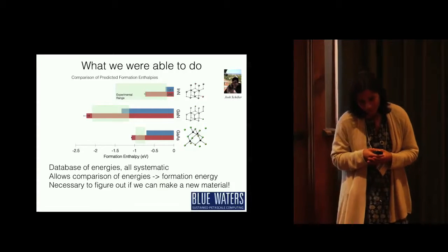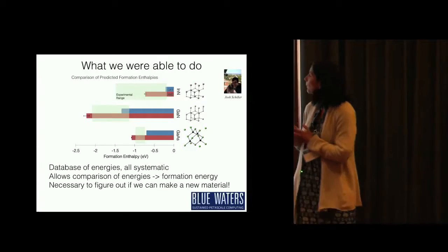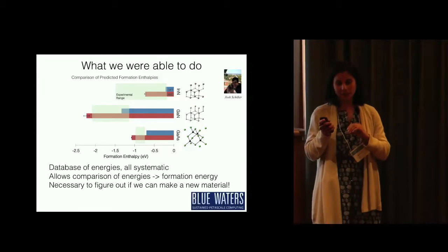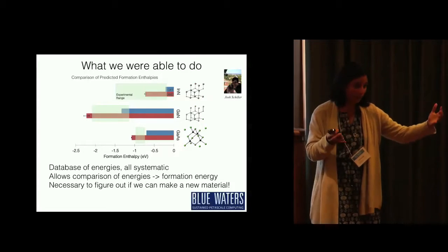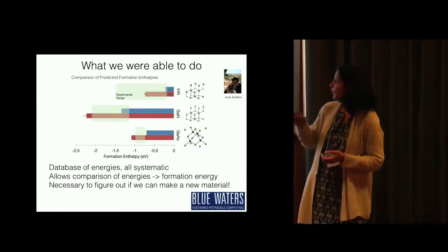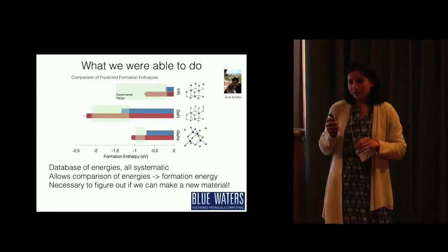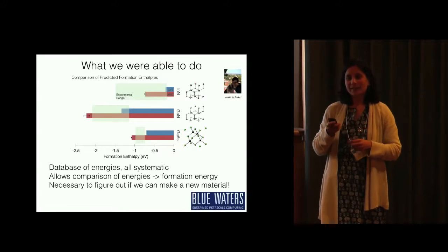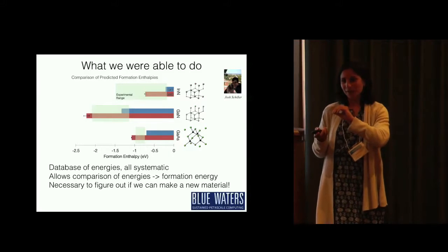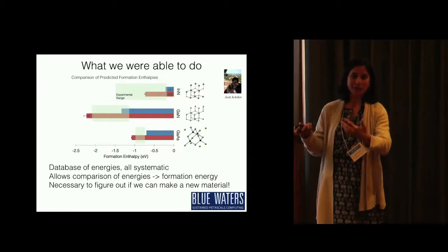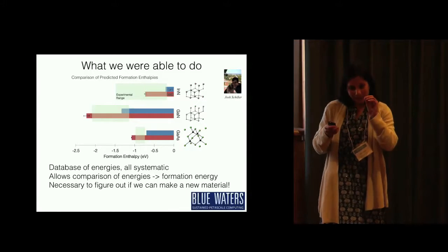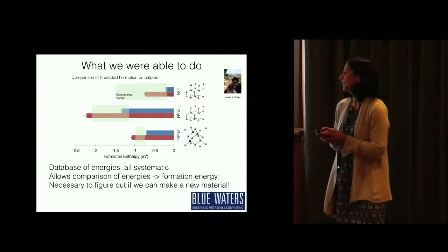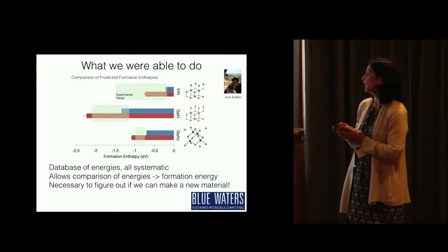The reason is that, take a semiconductor, gallium nitride, for instance, we need to see how stable that is with respect to decomposition to gallium, a metal, and nitrogen molecules. That requires a calculation of 3 different types of materials, a semiconductor, a metal, and a gas. It's not really the case that DFT has the same level of accuracy for all of these. We need a technique that can treat all of them on an equal footing, and that's what we get out of using an unbiased Monte Carlo approach.